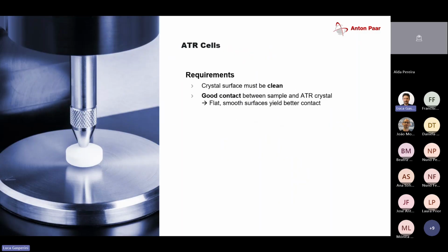Talking about FTIR, I said there is no sample preparation, so I just brought some requirements. Let's say you have an ATR crystal, and it's very important to stick to some rules. First of all, the crystal must be clean. Those instruments are very, very sensitive, so just breathing at the instrument will show you a CO2 peak. So it's very important that you clean it very thoroughly, so that you only measure the sample you actually want to measure, and not some external influence.